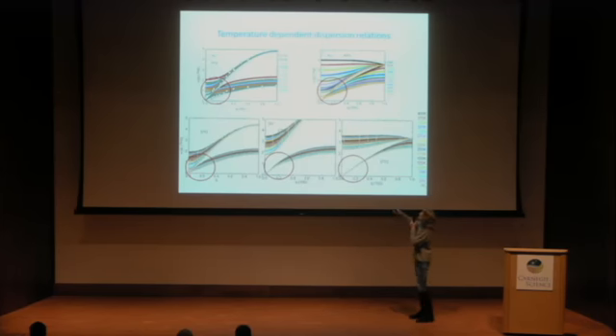If you look at barium titanate, then you see there is nothing like precursor dynamics because there's no interaction with the acoustic mode. Only if you come close to the phase transition temperature, then you can imagine that you have polar nanodomains or elastic nanodomains coming into play. In strontium titanate, it's very much like in lead titanate. There's easily the possibility for interactions between the two modes, which is less given in calcium titanate and absent in europium titanate.